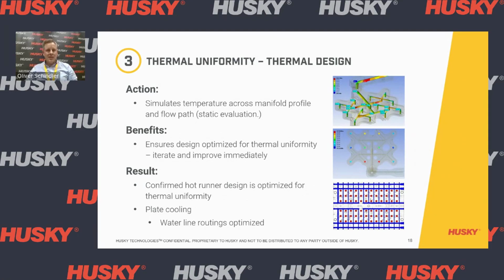The hot runner designer optimizes it in a way that the thermal uniformity of the system is acceptable prior to starting any manufacturing steps. And once there's something out of the rules, it will automatically end up at our desk, and we would directly go into a discussion or solutioning to find a way to get it better and optimized. So this procedure ensures that the system is individually adjusted and optimized for your application and resin requirements, and ensures that you have a consistent melt stream all along from the inlet till the outlet, as well on the hot runner blades on the outside, so that you don't have any hot spots there.